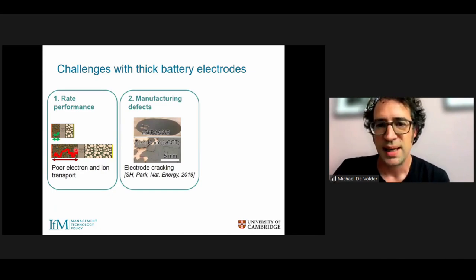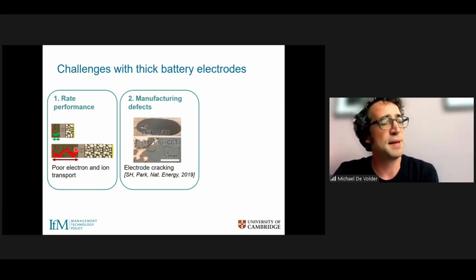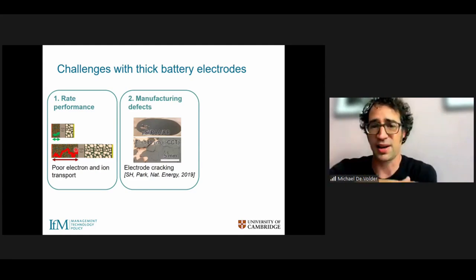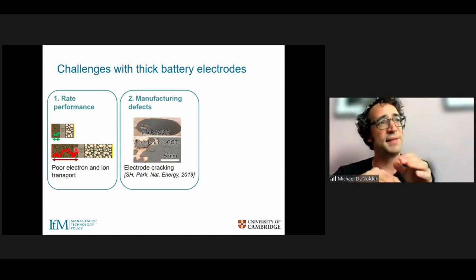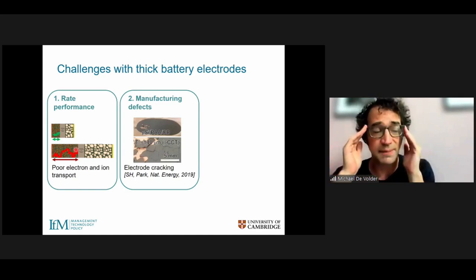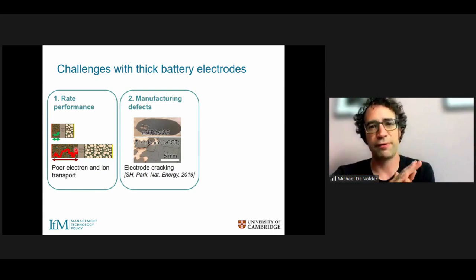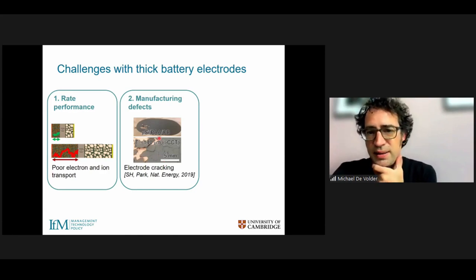The other problem is that in the current fabrication process of batteries, people take a slurry of the active materials with some binder and conductive additive, and they just cast it on a foil. And if the layer you cast is very thin, it will dry nicely and form a uniform film. But if you try to coat a thick electrode, during drying, cracking and flaking problems occur as depicted in the image in the middle here.